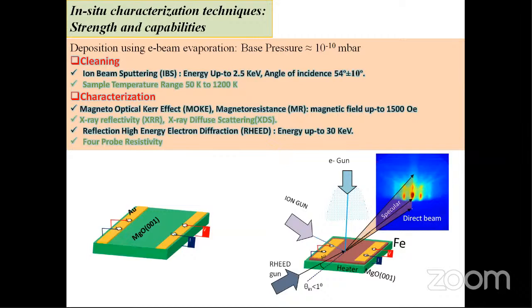Before loading the sample into the UHV chamber, first we have deposited Au gold of 13 nanometer as an electrode for transport measurement. This is just a schematic of the reflection high energy electron diffraction measurement, where this is the RHEED gun where the electrons come from and strike the surface, and the reflected electrons are collected on the fluorescent screen and make a diffraction pattern, and the image is captured by the CCD camera.